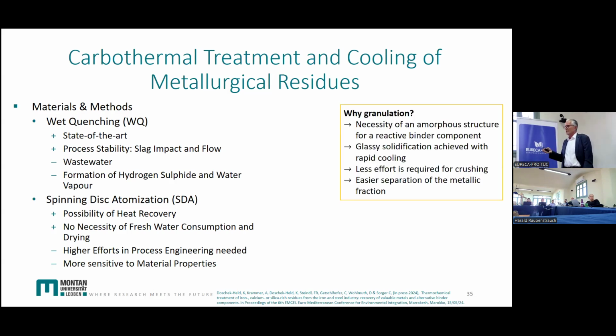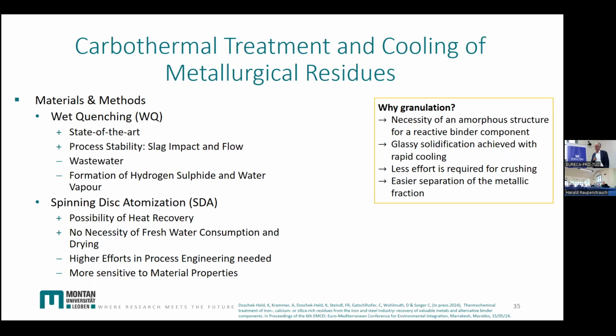So why do we need granulation then? Well, we need an amorphous structure to use it as a reactive binder component for the cement industry. And this glassy solidification can only be achieved by rapid cooling. If you cool too slowly, you produce wool instead of spheres, granulates. Another advantage is you need less effort for crushing it, and it's easier to separate the metallic fractions from it.